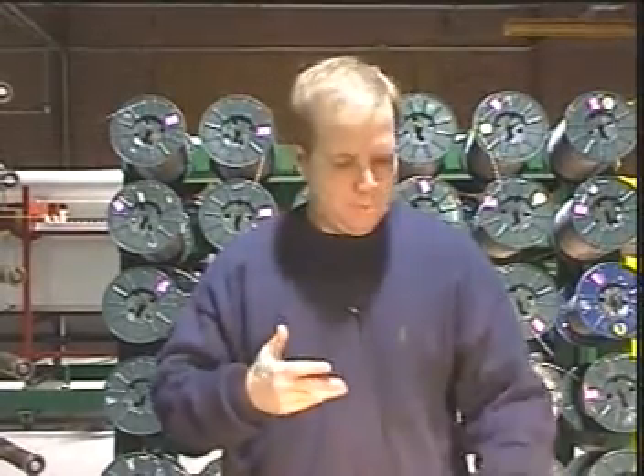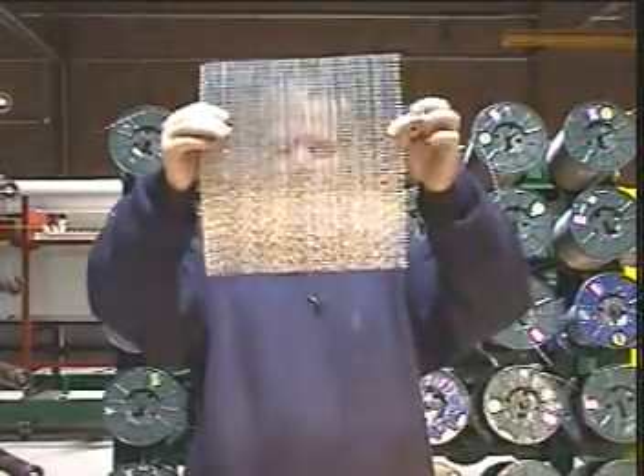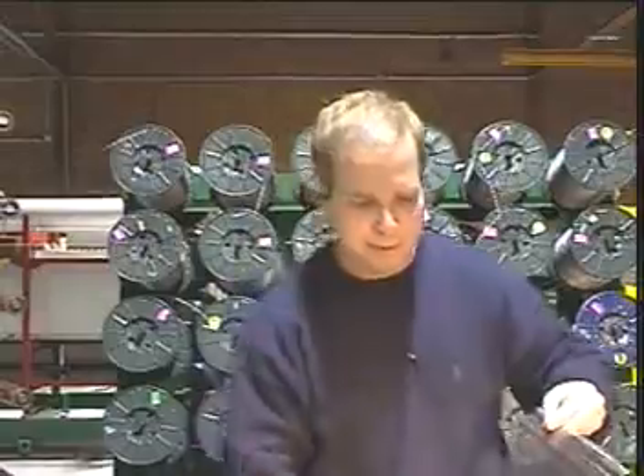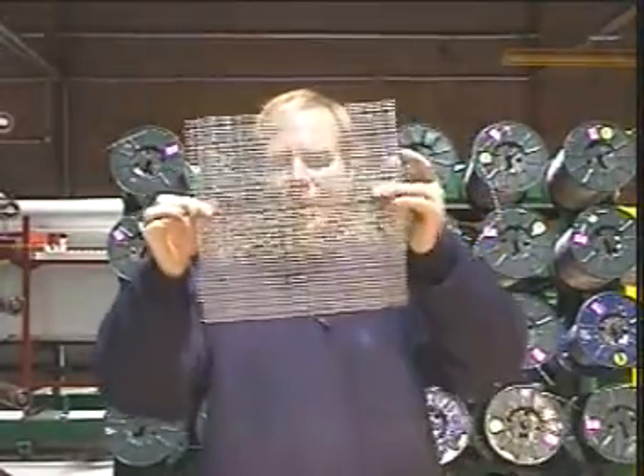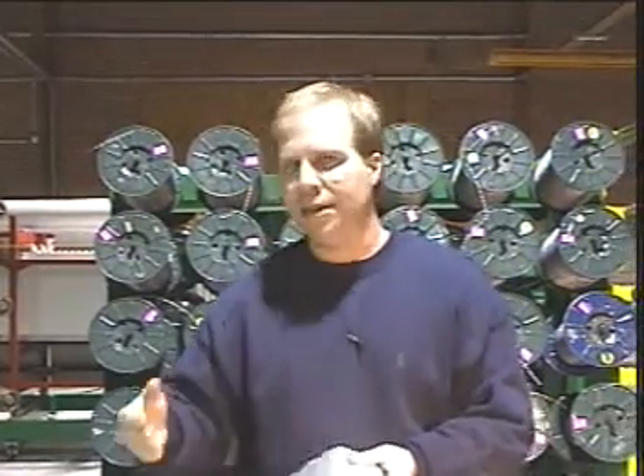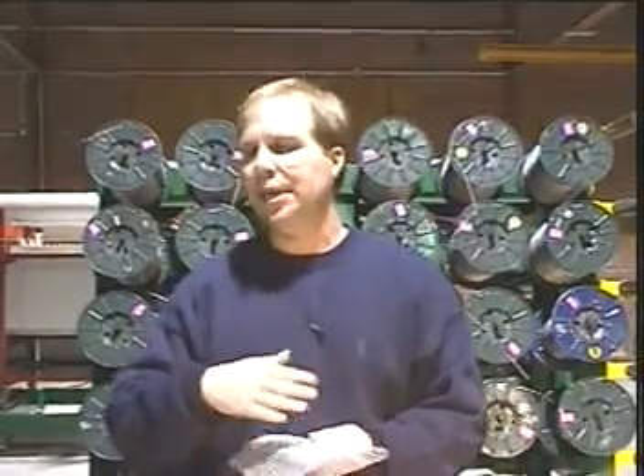One of the biggest things that all of this means is, when we sum it all up at the end of the day, making money in the molding business, a place where I have very strong roots, basically boils down to getting the reinforcement in the mold quickly, and 1 ply versus 5 plies versus 25 is going to make a tremendous difference just getting the material in the mold. Second, because the Hardwire is so much more permeable, and again, you kind of get a nice look through this, it's extremely permeable material in all kinds of different densities. It means that the resin is going to flush through this material 10 to 100 times faster than it would in a glass or carbon laminate. And in carbon, it is very dramatic.